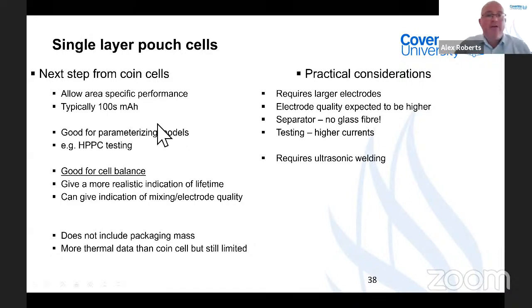And these are very, very good because they allow you to get area-specific performance. They'll allow you to go to much higher currents, so you can take away some of the issues you may see with the separators at higher rate testing. They're good for parameterizing models. So for instance, you can now reliably do HPPC testing, and they're excellent for looking at cell balance, the balance of your anode and cathode. They also give a very good indication around your mixing and electrode quality, but they don't generally include the mass of your packaging in there, and they still don't give as much thermal data.